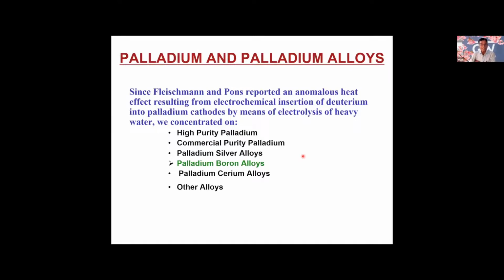And what we did after the announcement, we started looking into different types of material, including palladium. So we looked at high purity palladium, commercial purity palladium, palladium silver alloys, because there was some potential thought about that, and then palladium boron, palladium cerium, and other alloys. But I will concentrate more on palladium boron alloys because that's where we got positive results.